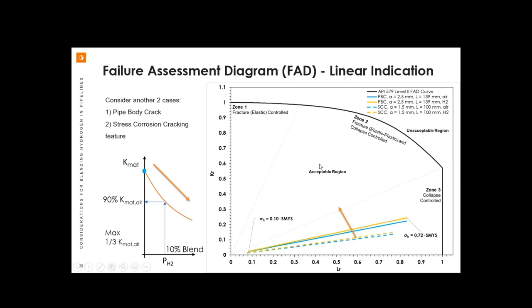So here are the other 2 crack features. We'll call them a pipe body crack and a stress corrosion crack, starting at 2.5 millimeters and 1.5 millimeters, but quite a bit longer in size, about 4 inches and just over 5 inches. Again, we note that they remain within the acceptable region of the FAD under our operating conditions, even with the 90% fracture toughness, which basically made the lines go from down here, the dotted lines, or the blue dotted line to the orange dotted line, and the blue solid line to the orange solid line. So not much change.